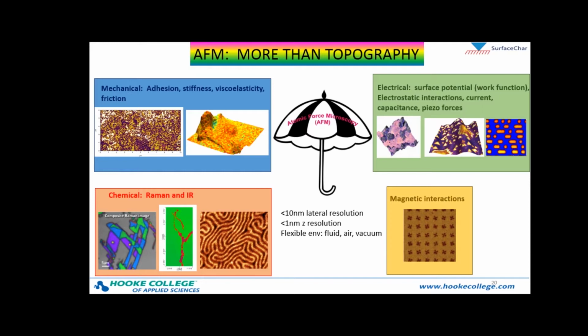Okay, so in summary, I hope I've been able to convince you that AFM provides information on more than just topography. I showed you a lot of applications that show the different surface properties that AFM can probe. So we started with mechanical, showing that AFM can provide very effective maps of different properties like adhesion and stiffness. It can also provide maps on viscoelasticity and friction. Did not show you those particular applications, but still possible.